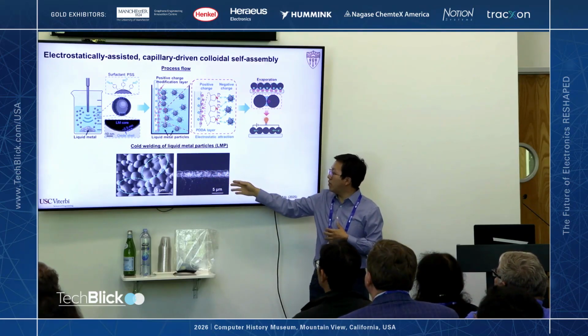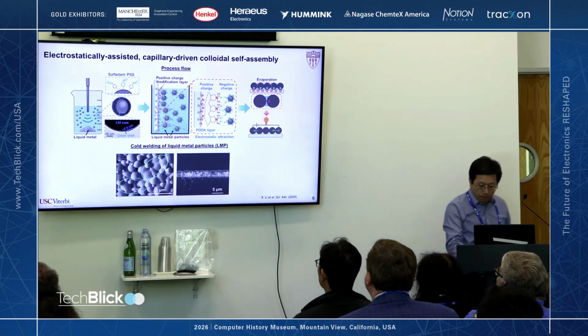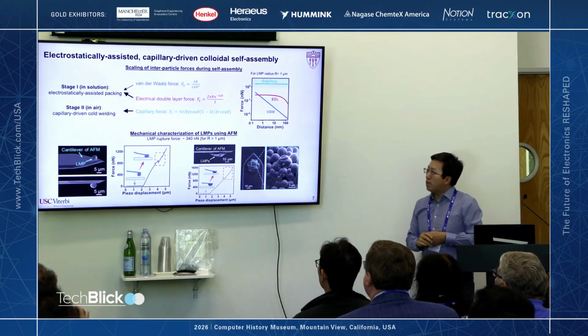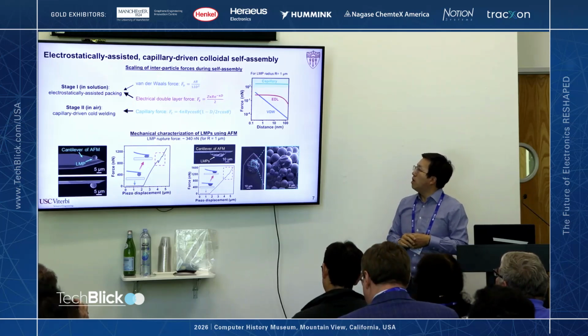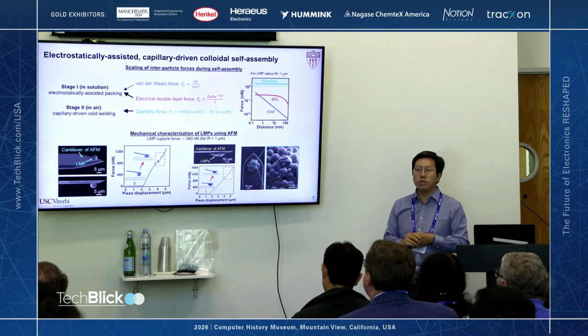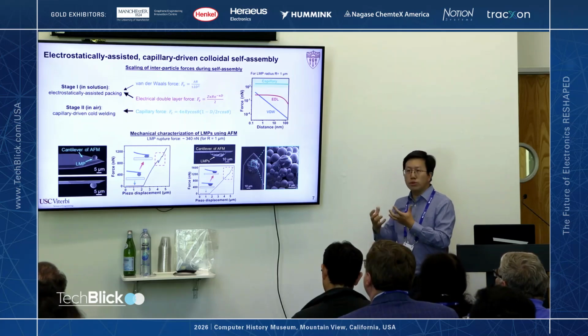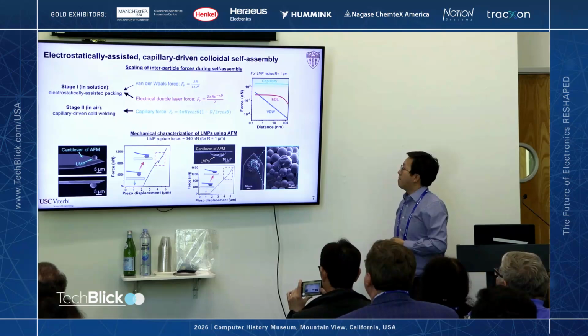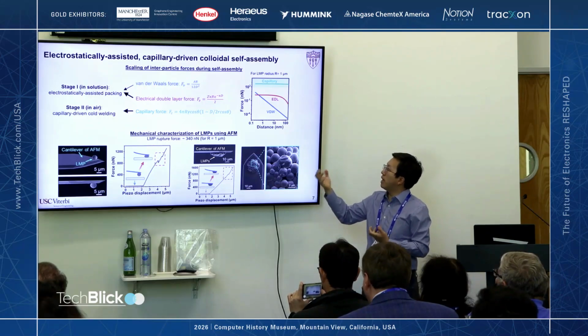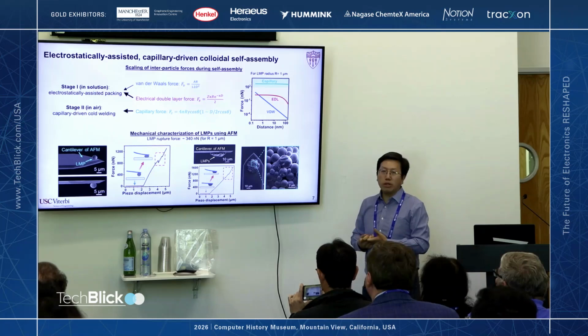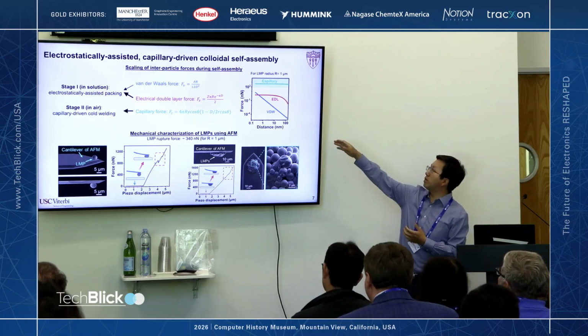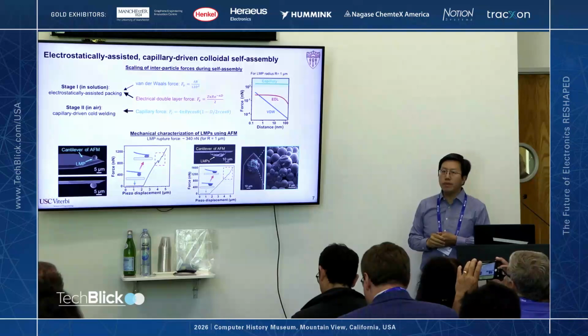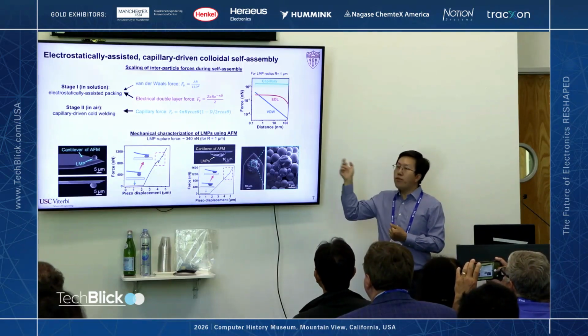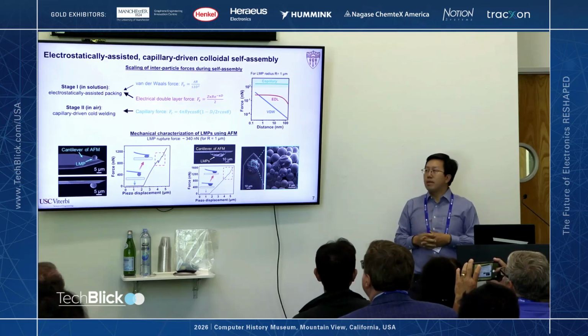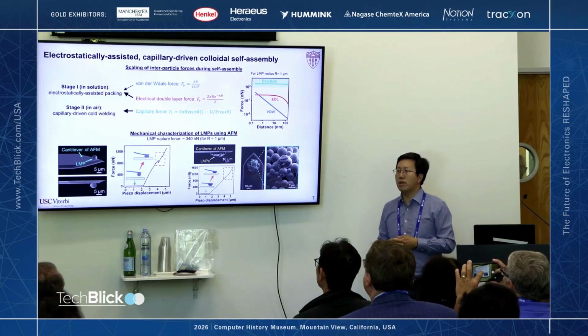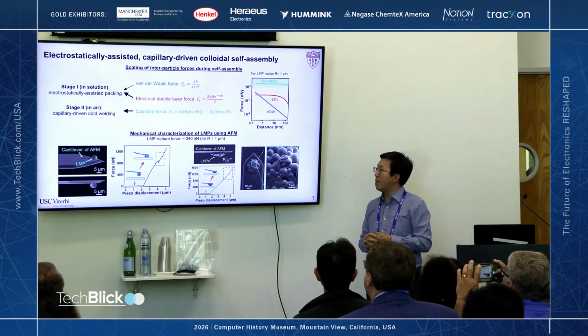We call this cold-welding. You can see very clearly the particles are connected internally. This is the side view. You can see about 2 layers of particles. We studied the process physics a little bit in detail. We were trying to understand what forces are causing the particles to break, basically. In the solution, there's van der Waals force, there's electrostatic force, but compared to capillary force, they are much smaller. The capillary force is about a few hundred nanonewton. We think this capillary force is the dominant force that breaks the oxide skin. But how much force is required to break the oxide skin? That was not known, it was not measured directly before.